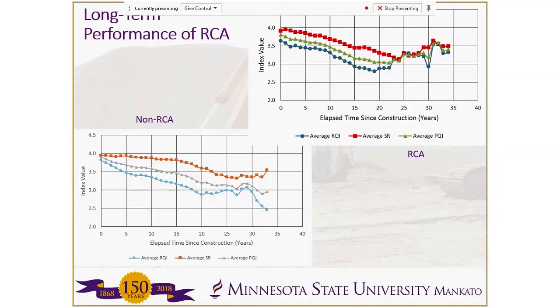So we studied the different pavement performance indexes. MnDOT has a nice database. They collect annually records of ride quality, surface distress, and pavement quality, and so on. So we tracked those, as you can see on these graphs here, looking at those different indexes. This is just showing the average values over time elapsed since construction. Looking at those indexes for both, the top one there is the recycled concrete. The bottom graph is for the conventional aggregate concrete. In both cases, we see the ride quality index is the lower curve. So ride quality tends to deteriorate the fastest out of these indexes.